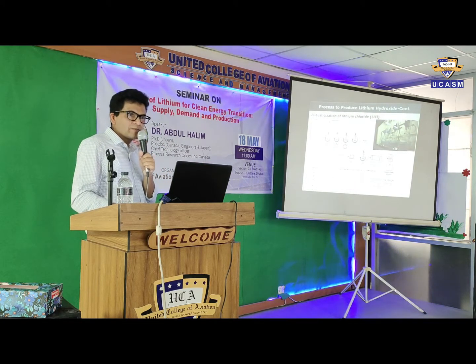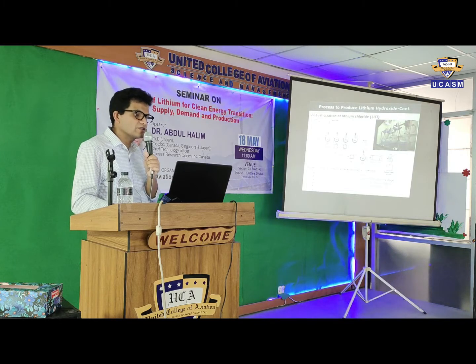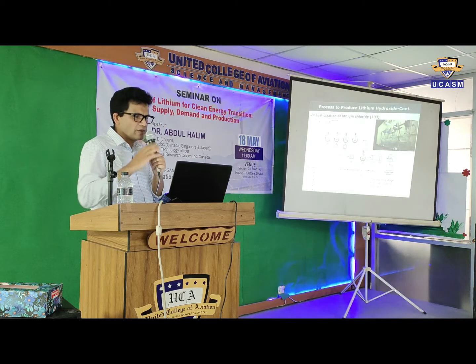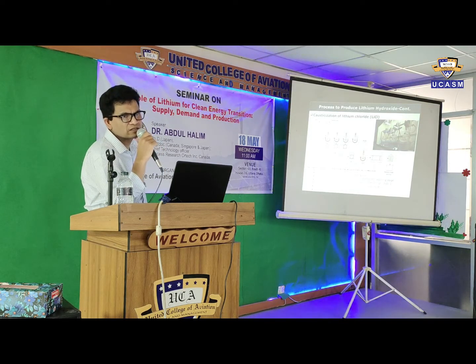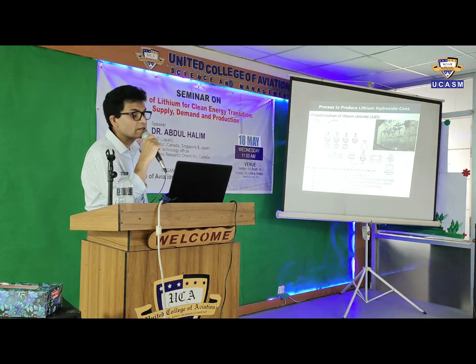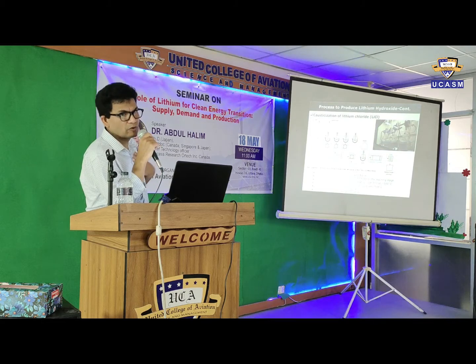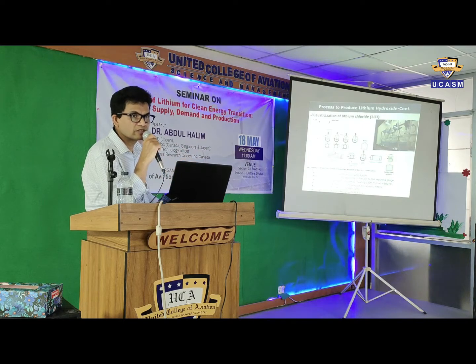The other one is chloride, the brine. So we also use the brine to make battery grade lithium hydroxide by using sodium hydroxide. So now we look at the why. Lithium hydroxide is precipitated by reacting with sodium hydroxide. Again, the solubility of lithium hydroxide is smaller than that of sodium hydroxide. These are the process steps we do in our place every day, every week, to optimize different flowsheets.